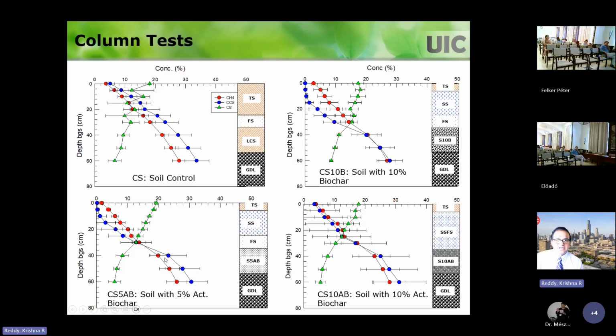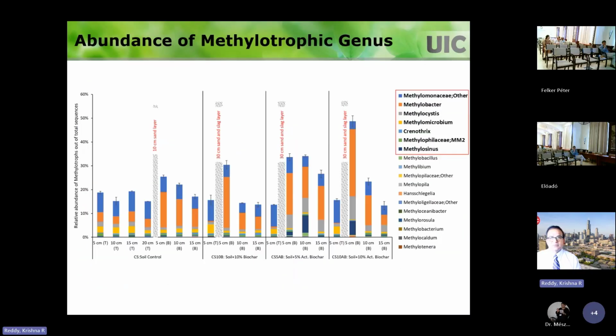But if I use these activated systems, you can see the concentrations of methane decreasing and CO2 increasing in the biochar amended soil layer. That's what we wanted to see. And once that CO2 comes into the slag layer, you can see it reduces. So in this profile, you can see nothing is coming out. Concentrations at the exit point are 0. So that would be like the best scenario you can think about.